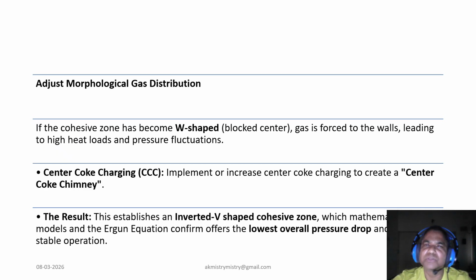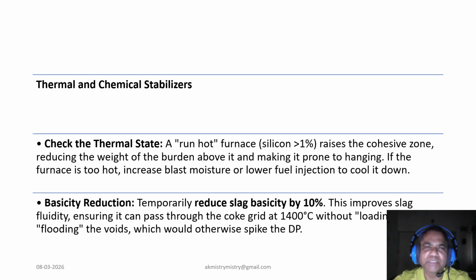Now watch your thermal state. A furnace that runs hot with the silicon over 1% can actually become unstable. It raises the cohesive zone, making the burden lighter and prone to hanging, where it stops descending. If the furnace is too hot, increase blast moisture or lower fuel injection to cool it down and keep the material moving, which is supposed to be our prime objective.